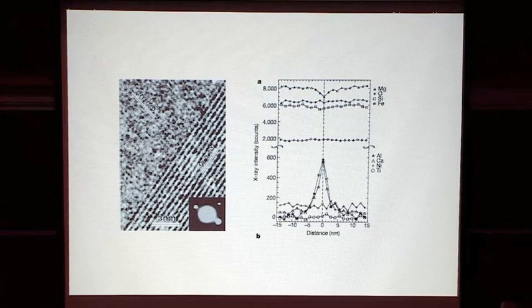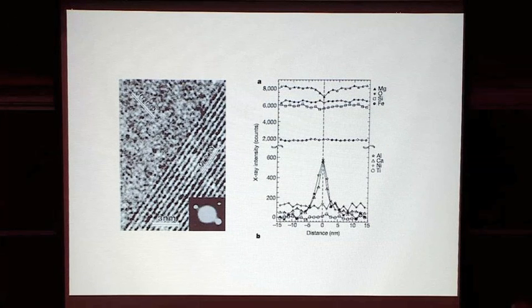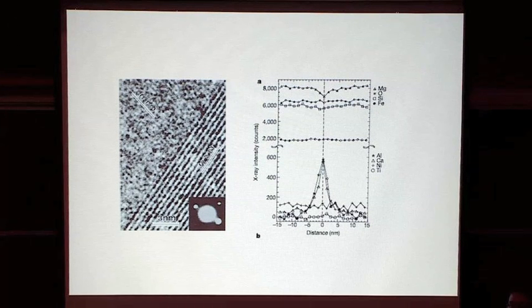Dave? Were such elements on the grain boundaries in the boundaries? Oh yes, I'm going to show you an example of that, and it doesn't even have to be this, but this definitely matters, right? If we want the grain boundary to migrate, it can migrate only as fast as the incompatible elements that are sitting on it are able to move. So yes, incompatible elements can definitely make grain boundary migration sluggish, and that's why people like Kohlstedt and Faul are interested in the relationship between grain boundary poisoning, if you will, and transport properties.